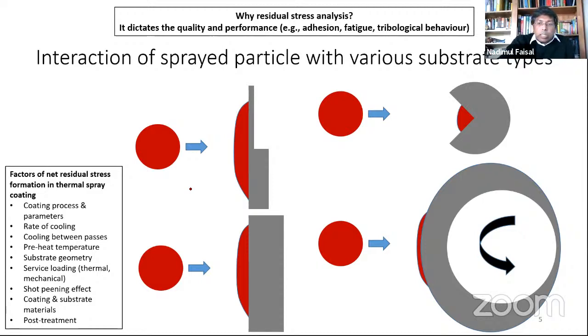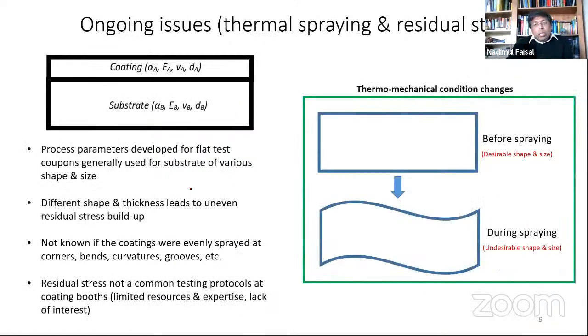Right, so this is what happens. Now, if you see on the screen, the desirable shape and size is the one you are spraying on. But during this thermal spray process, something happens on a very small scale. Some deformation will happen because of spraying at high temperature. And then you end up getting a substrate or sample which has changed in a few minutes or seconds. However, when you develop your process parameters, you assume a number of things. You assume the substrate is constant, with particular properties. However, these things change during the thermal spray process.